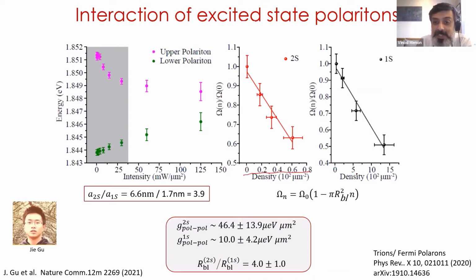So pay attention to the density of the carriers that are involved to shift your Rabi splitting by the same magnitude. You will see that the interaction strength is about 4 times the interaction strength of the 1s exciton, and that goes with the fact that the Bohr radius is actually scaling by the same value. So this was a very promising result that you can go to these excited Rydberg states. This is actually the first time Rydberg states in 2D solid state systems have been used. They have been used in cold atom systems for a long time. People have been using Rydberg states for blockade and so on over the last 10 years or so. But this work really shows that you can extend this to the regime of solid state systems, though it has to be at low temperature. So these experiments were all done at 4 Kelvin.